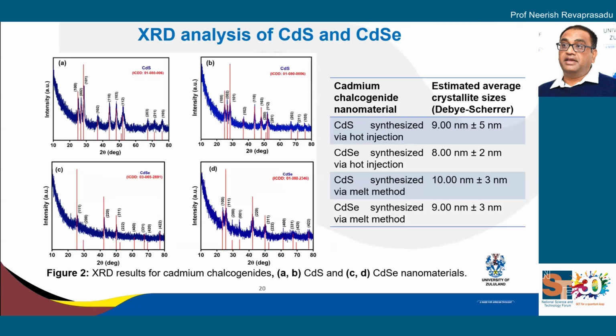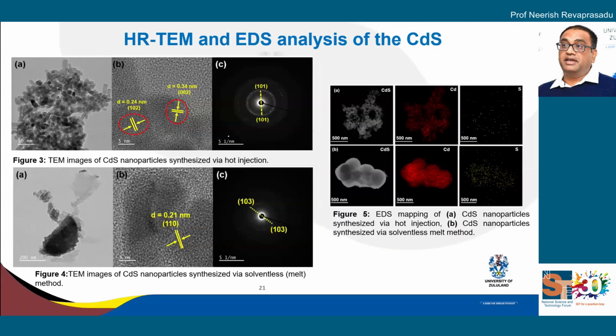Before we study them, we characterize them, and X-ray diffraction is one of the techniques. We can determine the phase and the purity of the phase, and we always like to make materials with good phase purity. Then we can view them under the microscope, which we have at UniZulu. We have a 25 million rand high resolution electron microscope, and here you see in this figure cadmium sulfide. You can see high quality quantum dots of cadmium sulfide, and then the very fine structure on the high resolution electron microscope. These are the lattice fringes, which are reflections of atoms, and you can see that they're quite pure, almost defect free, which we want. Then we can further characterize them using EDS mapping and selected area electron diffraction.